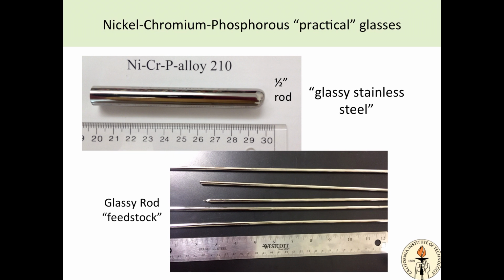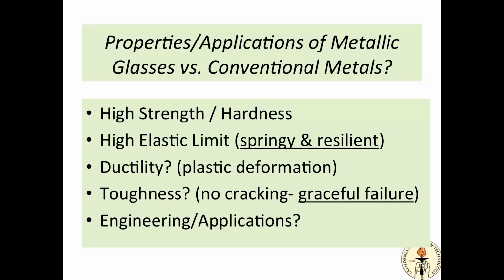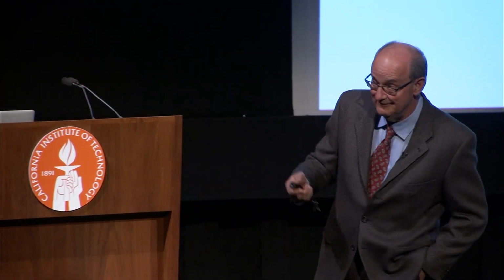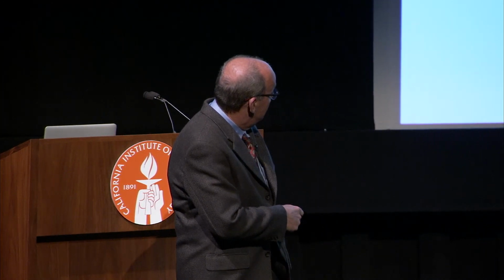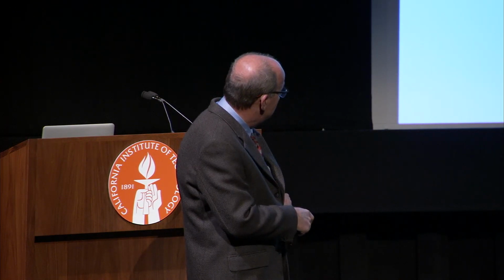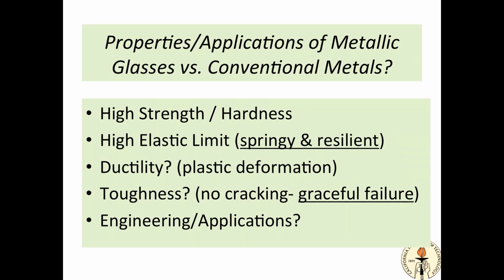And so, why? Well, turns out these metallic glasses are totally different than crystals. They deform differently. They have different mechanical properties. They're very strong and they're very hard compared with conventional stainless steel. They're very elastic and springy. At one time we tried to make golf clubs. Actually, John Daly and Paul Azinger used liquid metal golf clubs on the tour in 1998. And they're ductile. They bend like metal, but the mechanism for deforming and bending is different. I'll show you in a second. And so we get something that's very strong, like a ceramic, but tough like a metal. And this is interesting for applications to make things out of.